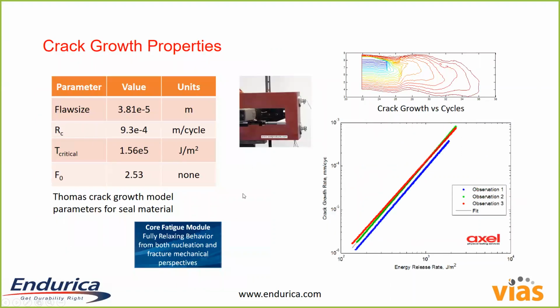Now, we not only have to define stress strain properties, but we also have to define the crack growth properties. We can measure those using crack growth experiments, right? So here we're showing the typical crack growth rate curves that we would measure. Here we're only looking at cycle dependent, but if we wanted to, we could include, like I said before, creep crack growth properties. And this is a list of the properties. We have a determination experimentally of this crack precursor, or the flaw size. In this case, it's 3.8 times 10 to the minus 5 meters, which is about 38 microns, which is pretty typical. Then the strength of the material TC, and the power law slope F naught 2.5. I believe this is a polyurethane that we're looking at.